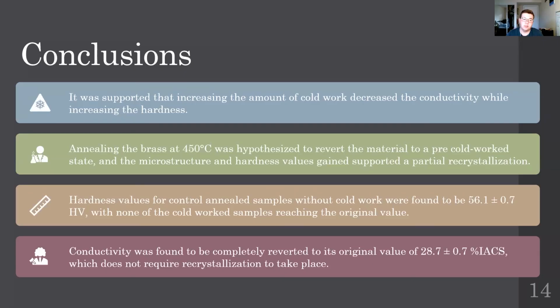So looking at our conclusions, it was supported in our hypothesis that increasing the amount of cold work would decrease the conductivity while increasing the hardness. And it was also supported in our hypothesis that when we annealed the brass, it could revert the material to a pre-cold work state. And the microstructure and hardness supported a partial recrystallization, that we didn't completely reach that pre-cold work state, but we almost got there. And with the hardness values themselves, none of the cold work samples reached that original value, which supports partial recrystallization.